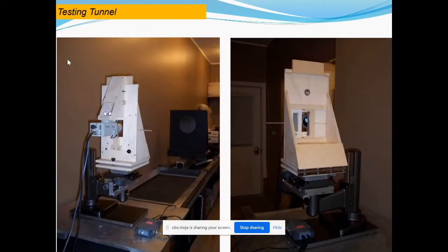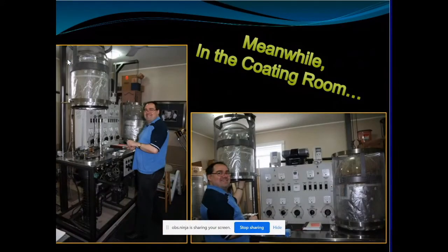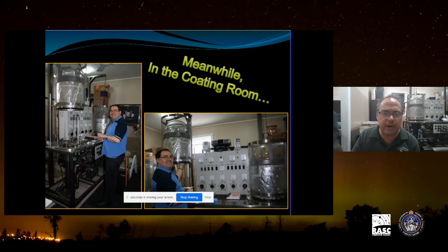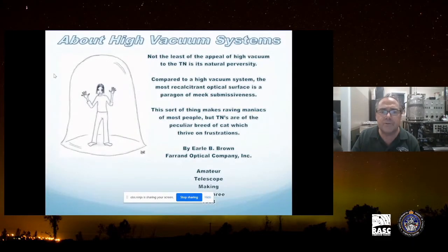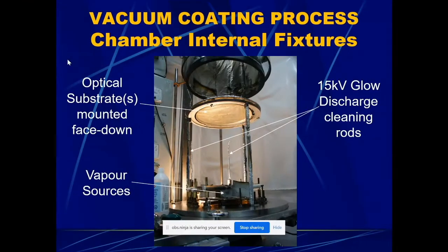We have an optical testing tunnel that's all computerized. And inside the coating room, we have a dual bell jar system. One of them is strictly for doing dielectrics and silvering, and the other chamber is used for enhanced aluminum coating. So this is a vacuum. Most of the technology that you see here has to do with creating a vacuum, so there are a lot of pumps and also electrodes.